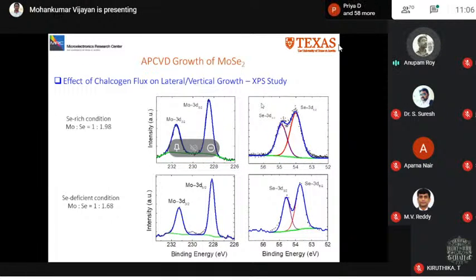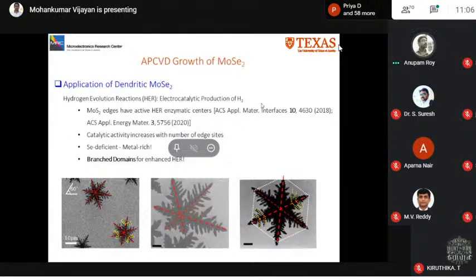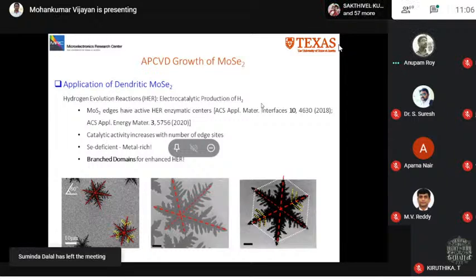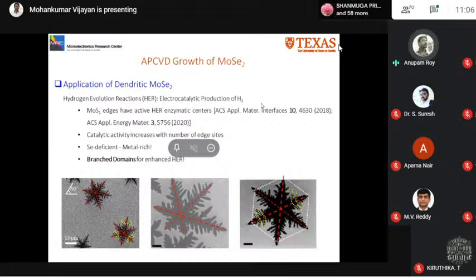In the next one, the electrocatalytic activity typically occurs at the edge sites. In the case of MoS2, it is reported that the edge sites and defects of sulfur atoms, that is the unsaturated states and vacancies, can enhance the HER performance. It is also reported that 1T structures, which are metallic, show better HER performance than semiconducting 2H phases. Now dendrites and fractals, as we observe, differ from the ideal stoichiometry and form metal-rich films. Thus, it will be an interesting area for further studies.